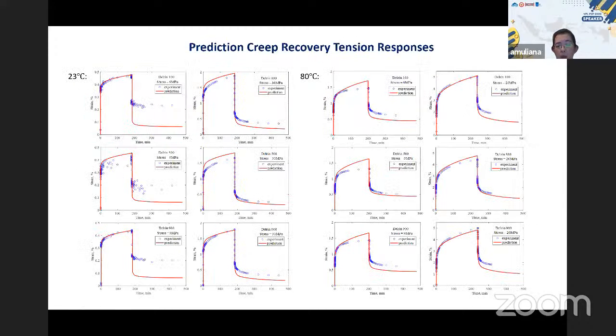Now, just to compare how the model looks with the experiment. These examples show the creep recovery under tension at two different isothermal temperatures. The left side is at room temperature and the right side is at 80 Celsius. Now we have all these responses for the three different POM, which we call Delrin 100, 500, and 900, at two different stress levels. The left side is low stress level, the other one is higher stress level. The solid line is the response from the model, while the symbols are the response from the experiment. As you can see, the model can capture the experimental response quite well. So this is for the creep recovery.